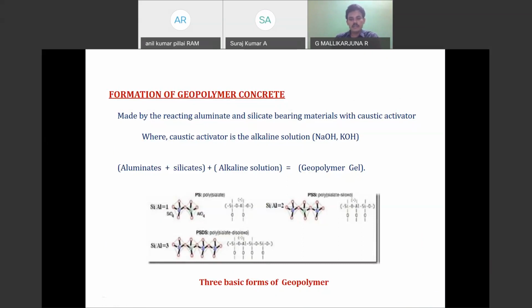Whenever you maintain the silica to alumina ratio as 1, you get tetrahedral structures like this, that is a polysilicate. If you maintain the silica to alumina ratio as 2, you get the polysilicate siloxane. And if you maintain the silica to alumina ratio as 3, you get the polysilicate disiloxane. These are the 3 basic forms based on your ratio.